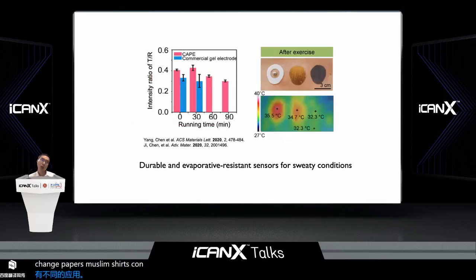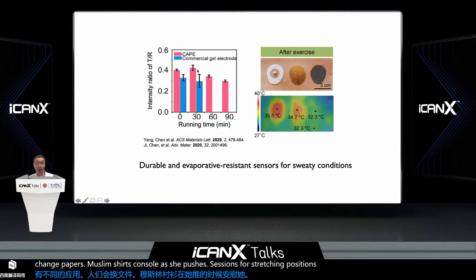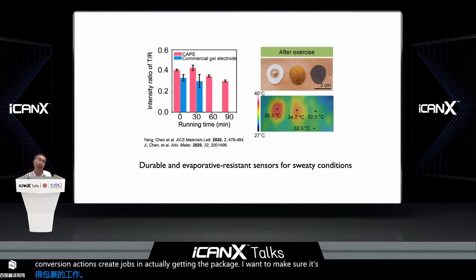We also put a lot of effort into developing durable and evaporation-resistant sensors for sweaty conditions, especially in Singapore. This is a really big issue, right? Singapore has high temperature and humid conditions. For conventional electrodes, commercial gel electrodes, which you get from the hospital or in the market, if you want to measure ECG or EEG for electrophysiology measurement, you will find after 30 minutes you cannot get any data anymore, because the electrode cannot adhere to the skin anymore. And then we developed our electrodes.